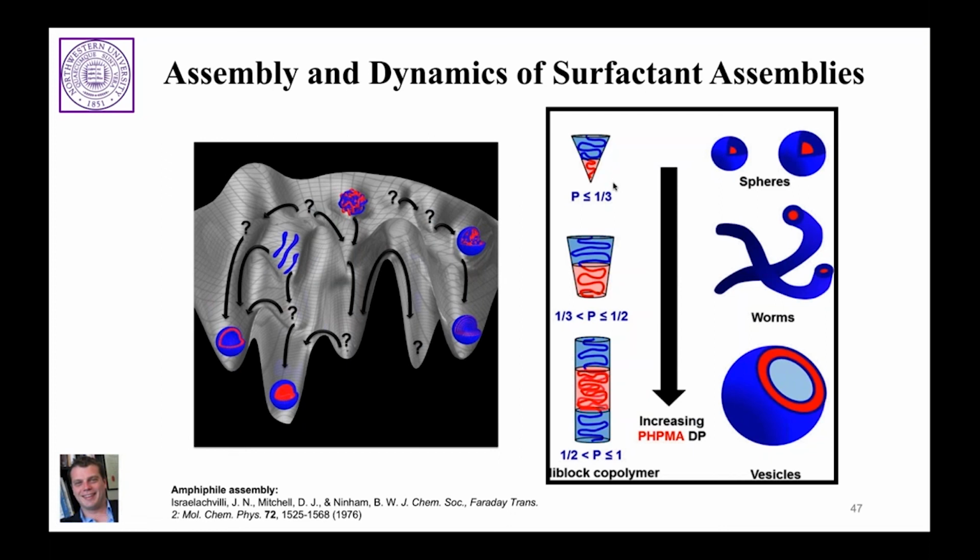And so you drive the particle to form by excluding water from the core, which is now hydrophobic, with the hydrophilic shell on the outside facing water. And in this way, you can imagine encapsulating drugs on the internal portion of a spherical micelle, as shown on the top. Now, as the geometry of the surfactant changes, the equilibrium structure changes to this more lamellar type architecture, as shown down on the right-hand side as a vesicle. And this is where we imagine the surfactants as packing as cylinders rather than as cones, giving us this flat surface on the nanoscale.